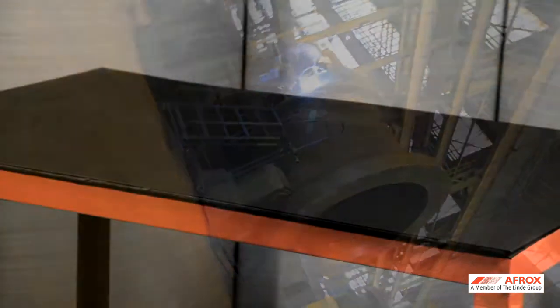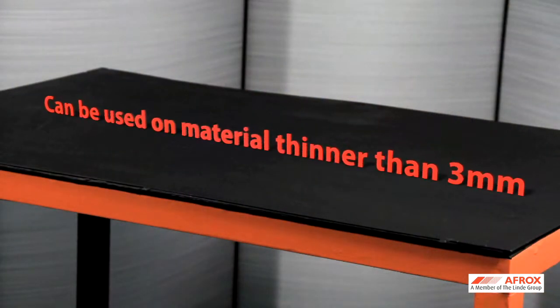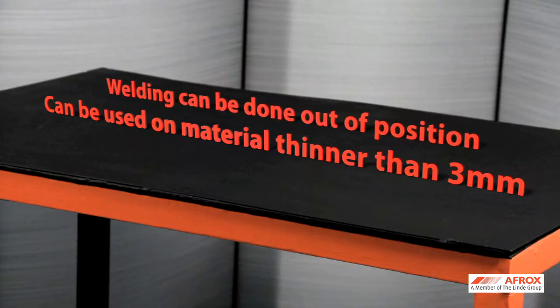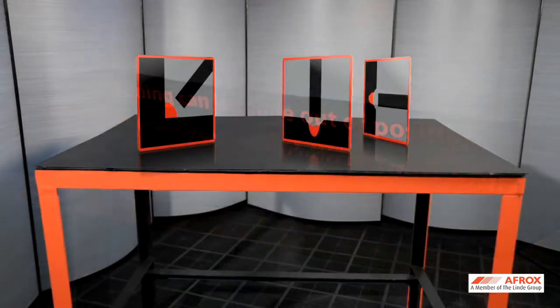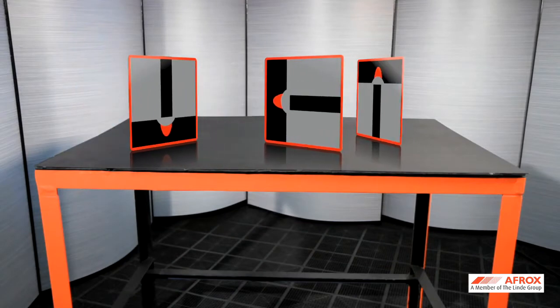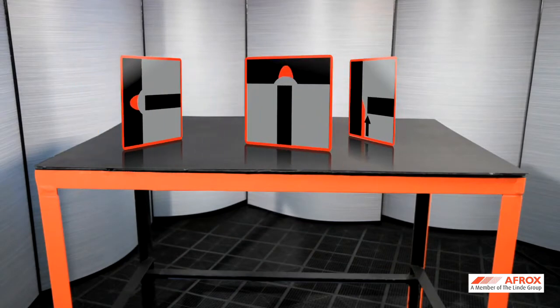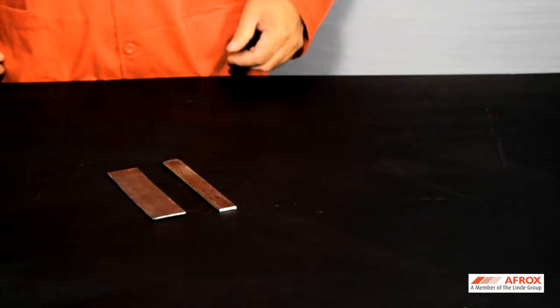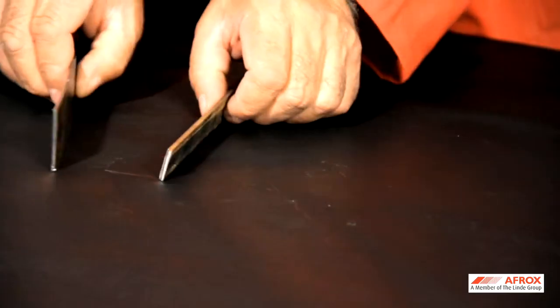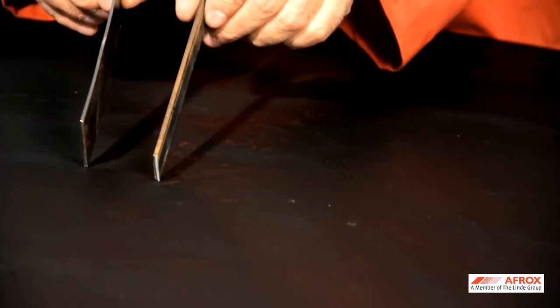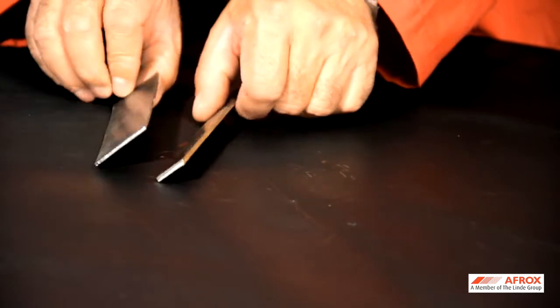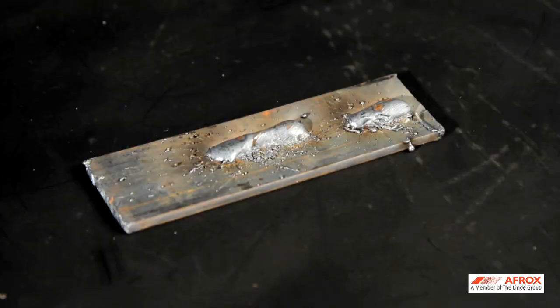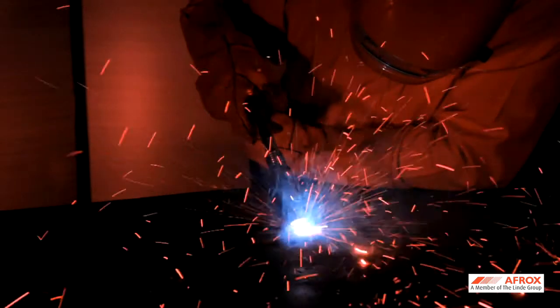The major advantages of the dip transfer is that it can be used on thinner materials below 3 mm and welding can be done out of position, for example vertical and overhead welding. The disadvantage of dip transfer is that it is not suitable for thicker materials and could result in lack of weld penetration and increased weld spatter.